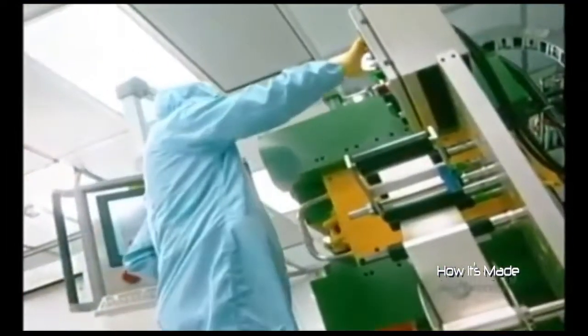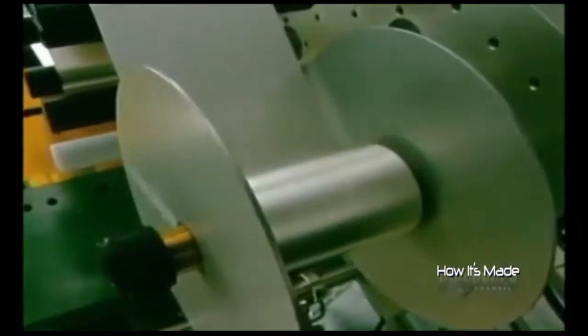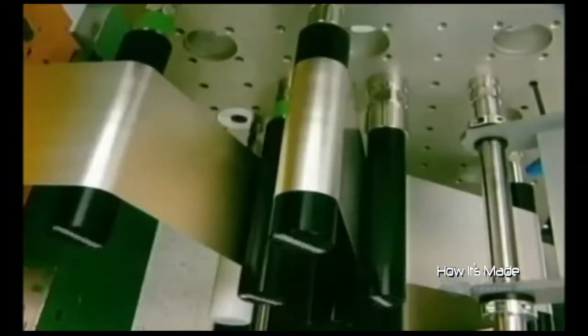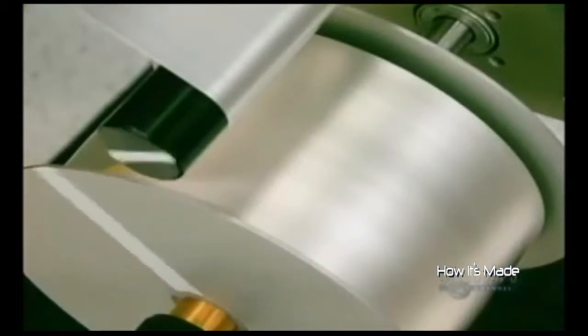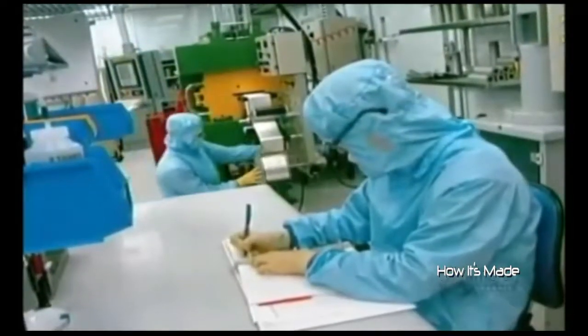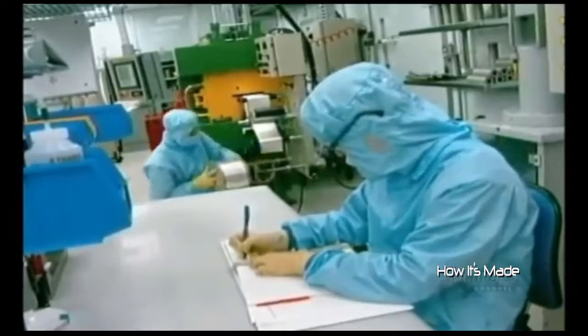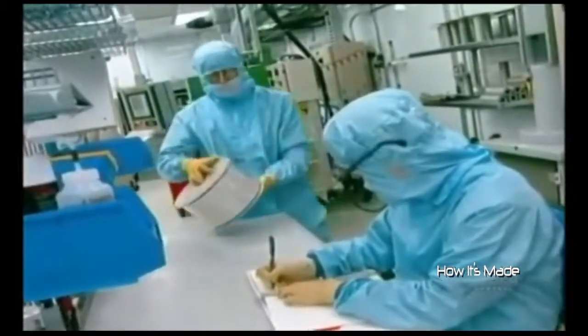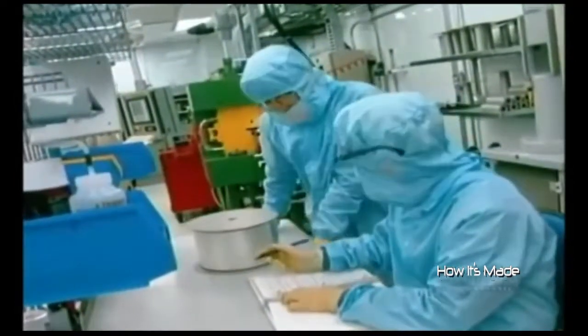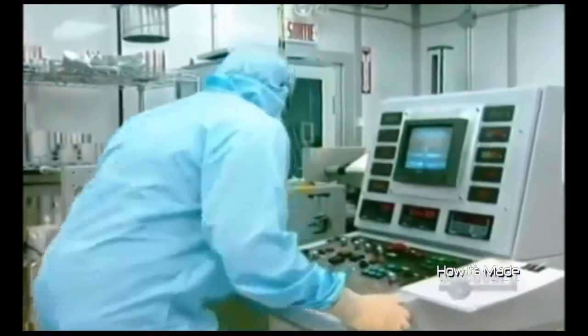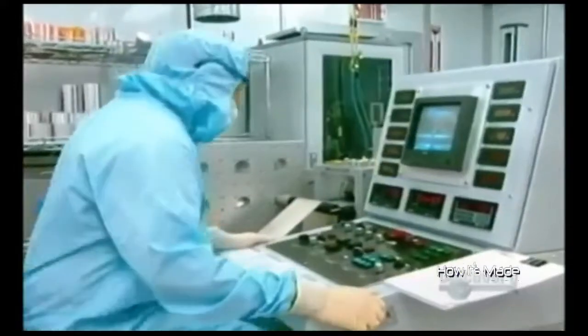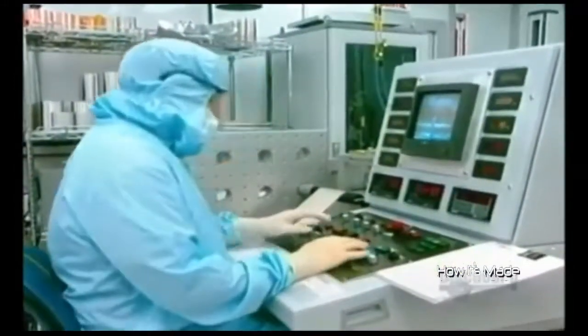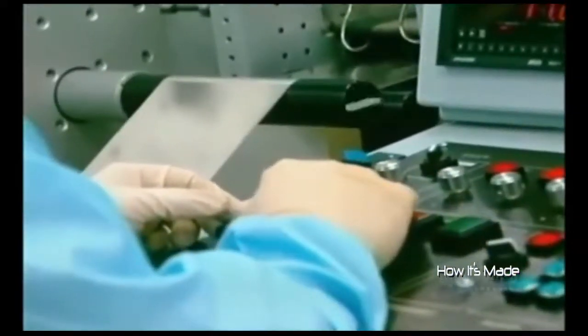Placed on a roller, it is carried to the laminator. At room temperature, it's thinned once again. In just 20 minutes, the 5-kilo ingot will have been transformed into a thin, 250 micron sheet, some 200 meters in length. This laminator completes the thinning of the sheet to between 20 and 40 microns. The resulting 2-kilometer-long sheet will allow for the fabrication of 210 battery units.